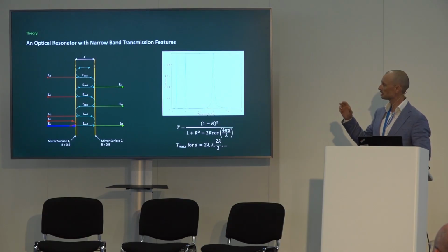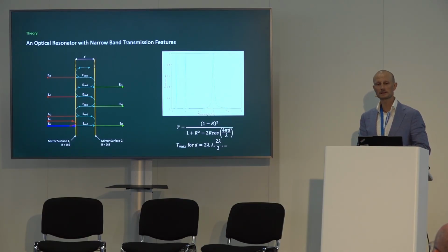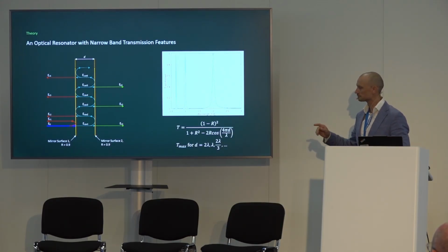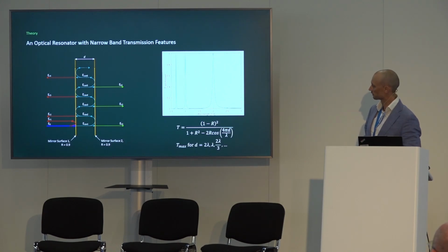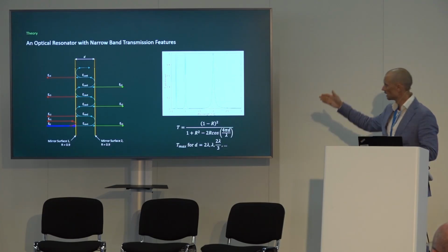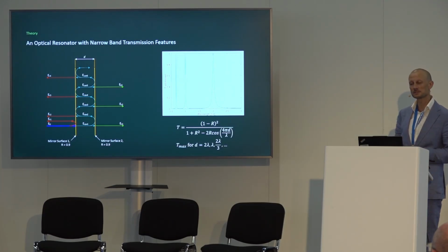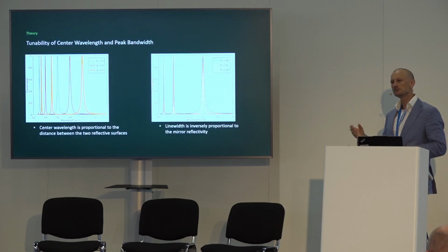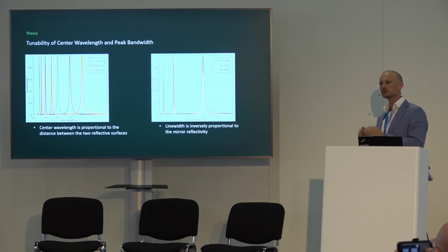Now, naturally, two mirrors should reflect a lot of light. So for most wavelengths, you get very low transmission. But for certain wavelengths, where this condition is fulfilled, you can get very high transmission, all the way up to 100%. And that creates these nice peaks in the transmission spectrum that you see to the right. These peaks can be moved back and forth by adjusting the distance between the mirrors, and you can adjust the bandwidth of each peak by adjusting the reflectivity of the mirrors.